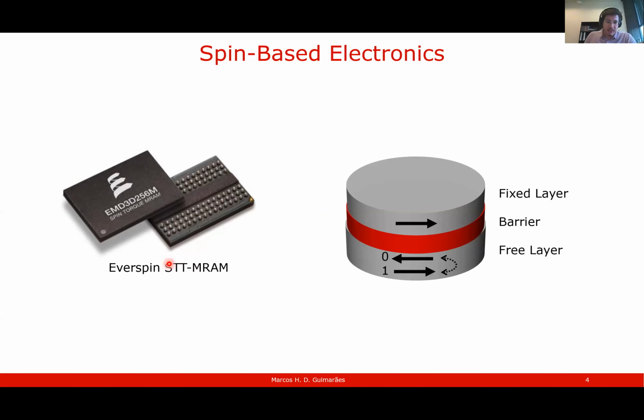And these spin transfer torque RAMs work with a memory cell that is basically a magnetic tunnel junction, which means that we have two magnetic layers separated by an insulating barrier. And then we can read and write information by flowing the current through it. The resistance is high if these layers are pointing with a magnetization anti-parallel, so one pointing to the right, let's say, the other one pointing to the left. This converts into a bit zero.